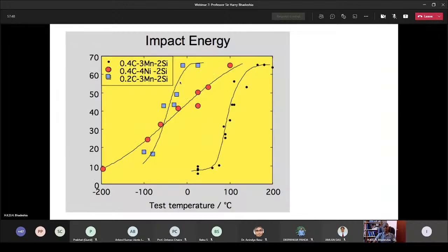And sure enough, when you measure the toughness, there is a change in the impact transition temperature by minus 200 degrees centigrade for both of these steels. You can see this is the high carbon steel, but with the T0 curve moved to higher carbon concentrations, and we've got really good toughness at low temperatures. And this is the X bar being reduced from 0.4 to 0.2. Very simple calculation. You have dramatically improved the toughness of the steel. And I emphasize that the strength is not compromised. In other words, we get the same strength in all three, about 1600 megapascals,